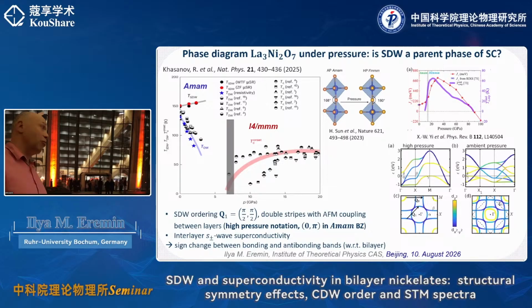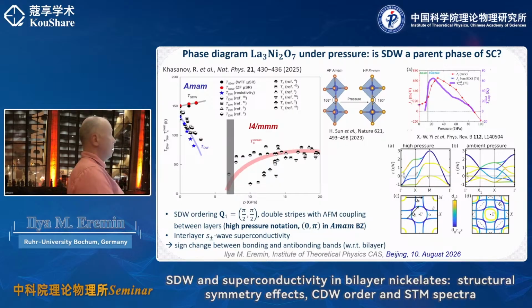And then the question, however, is if you now look at the fermiology at high pressure, that's what you've seen until now, right? So you have this alpha, beta, and gamma pocket. And you compare it to the fermiology of the orthorhombic phase. It actually turns out that the fermiology is very, very similar, if you just take into account that you need to fold your original tetragonal Brillouin zone, because now you have 2 atoms per unit cell. Yeah, so you have basically 4 atoms per unit cell, right? And if you do this, then you see that there is a folding.